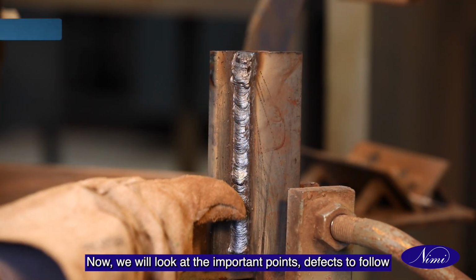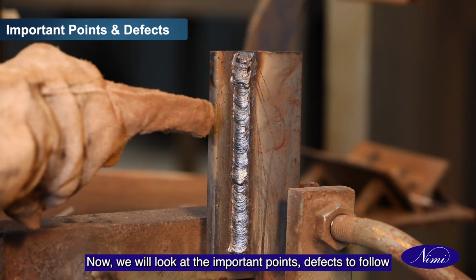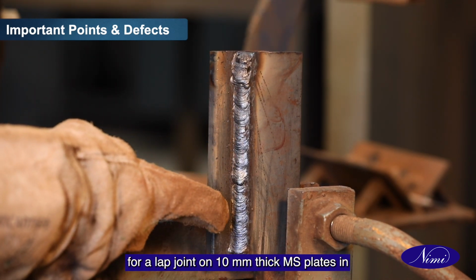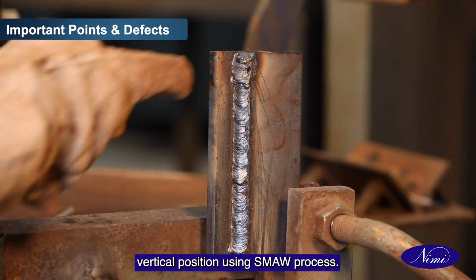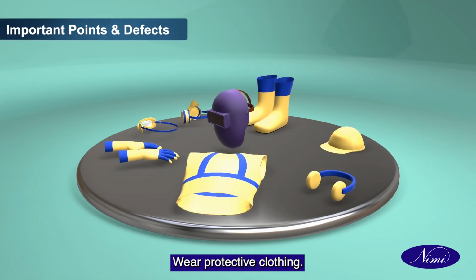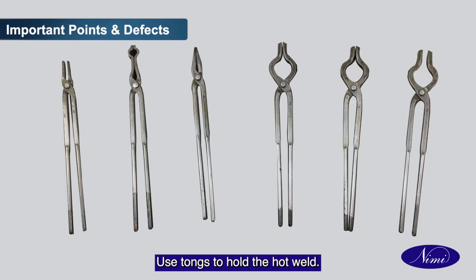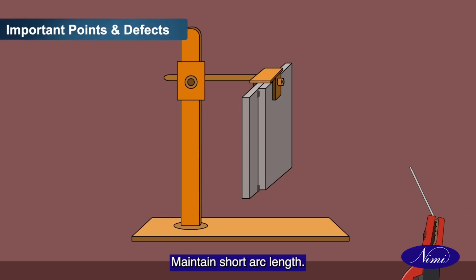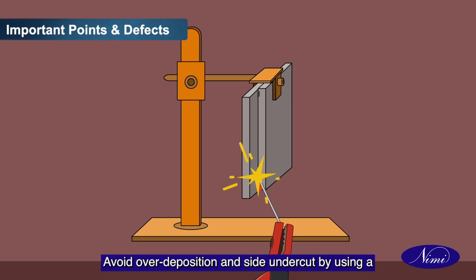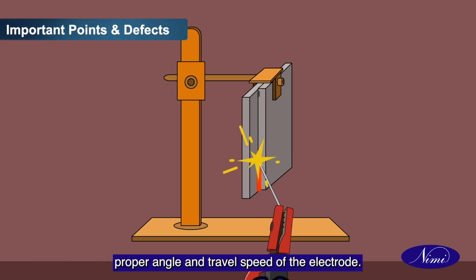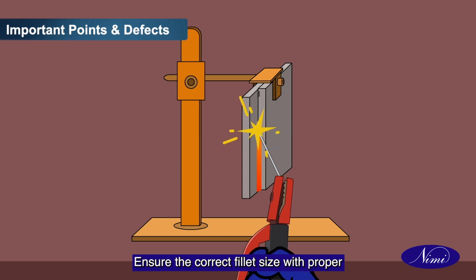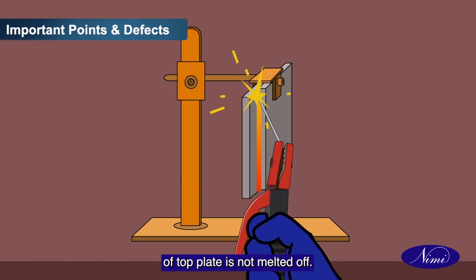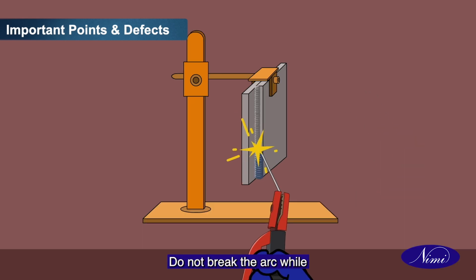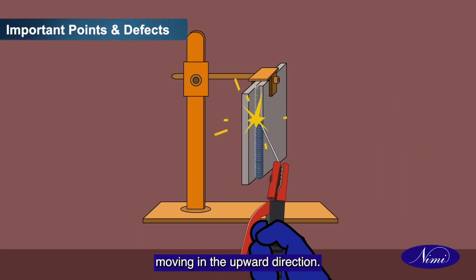Now, we will look at the important points, the defects to follow for a lap joint on 10 mm thick MS plates in vertical position using SMAW process. Wear protective clothing. Use tongs to hold the hot weld. Maintain short arc length. Avoid over deposition and side undercut by using a proper angle and travel speed of the electrode. Ensure the correct fillet size with proper bead profile is obtained and the edge of top plate is not melted off. Do not break the arc while moving in the upward direction.